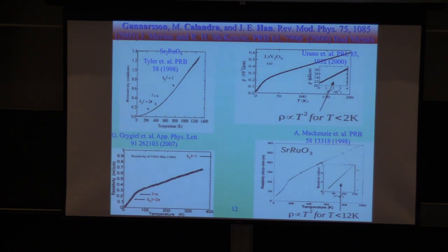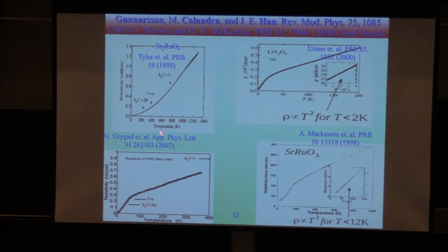Another example of why the strongly correlated systems are so interesting is because they're extremely resistive. So here I just collected for you a few examples of strongly correlated materials, ruthenates, vanadates. Cuprates do the same thing. What I want to point out here is that if you measure the resistivity versus temperature, the resistivity of these systems at high temperatures far exceeds what's called the Mott-Ioffe-Regel limit, which is around 100 microohm centimeters, which would be here. And the reason why this is so puzzling.